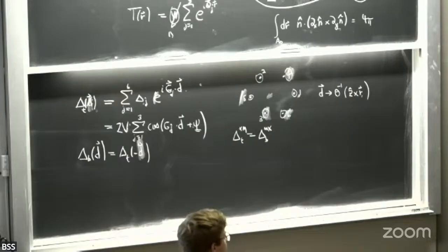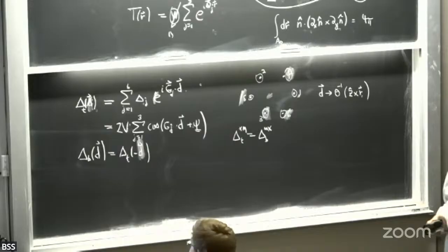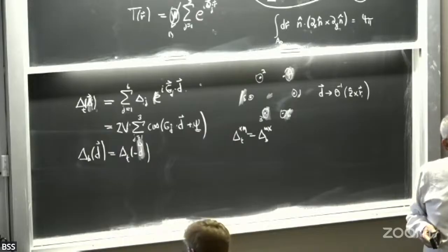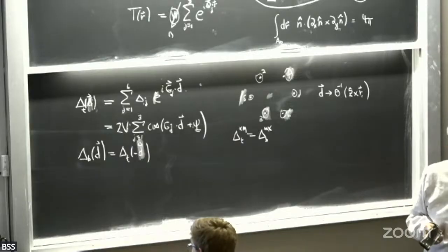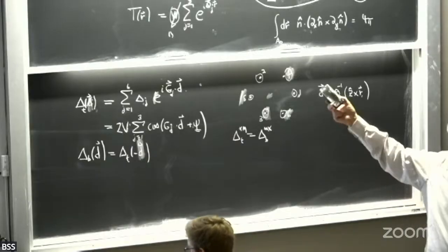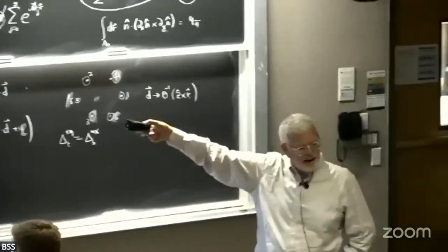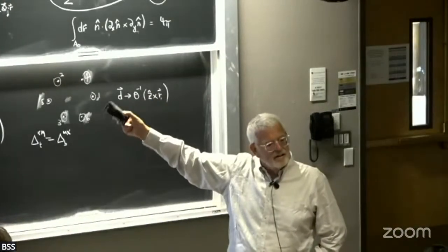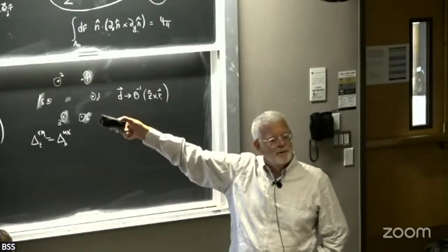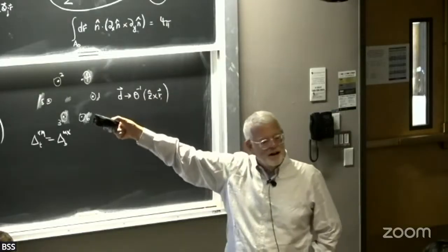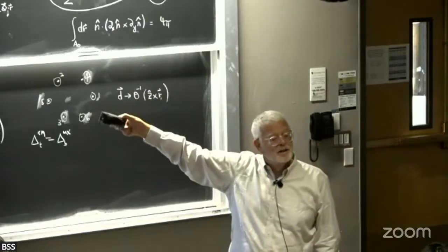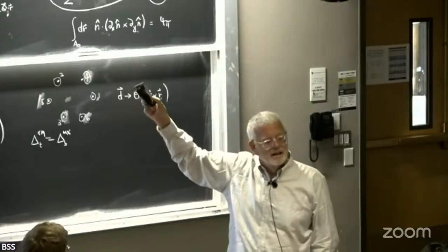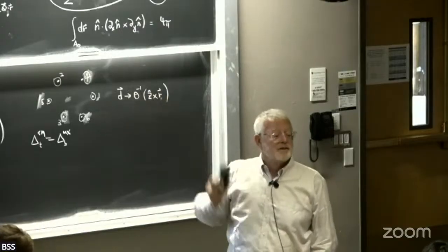What we did at the time is we just argued phenomenologically, building on what we did with graphene. We did band structure calculations for all the high symmetry stackings, and then we fit it, okay? But the way we do it now, and we certainly have done this over again, you can do a DFT calculation for every stacking. And this is a partial representation of the layer dependent parts of the tight binding Hamiltonian as a function of stacking.